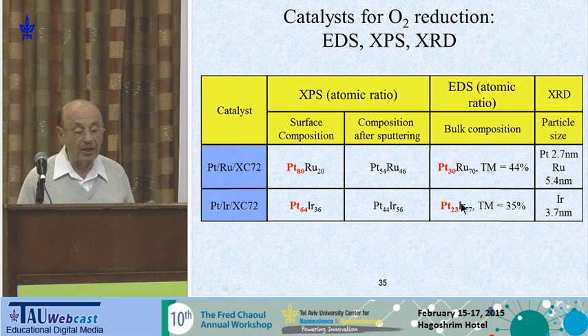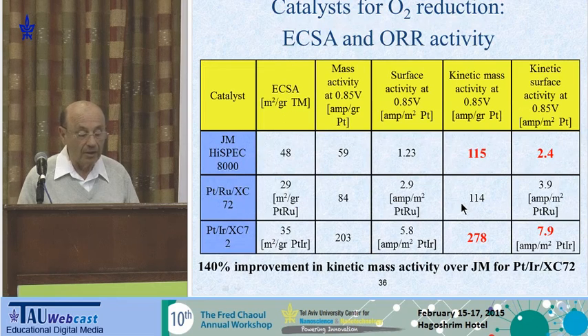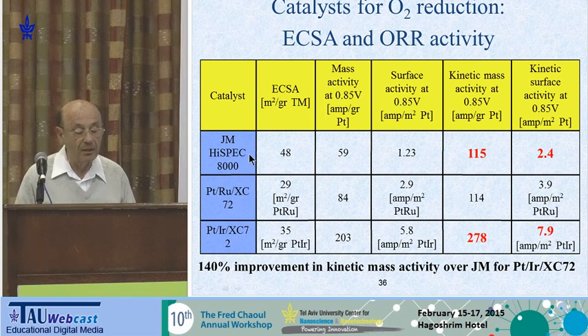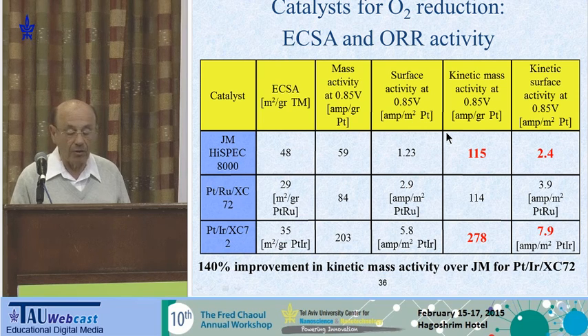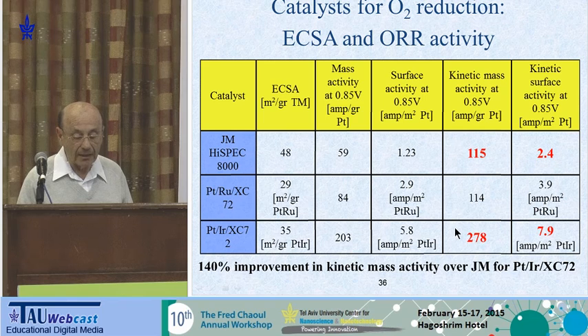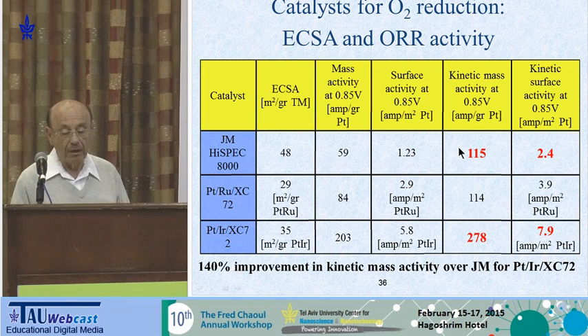So the last thing to do is to measure the activity. That's nice, but it's not enough. So we purchased Johnson Matthey HiSPEC 8000. This is the best catalyst we were able to purchase, and we compare our catalyst to this one. There are 2 parameters for comparison. One is practical, economic, the dollar value, and we measure kinetic mass activity in terms of ampere per gram of platinum or ampere per dollar. And we see that with this catalyst we get 2.5 times more activity, higher ampere per gram of platinum, than the commercially available catalyst. The cost is about the same. So these are the economic parameters.